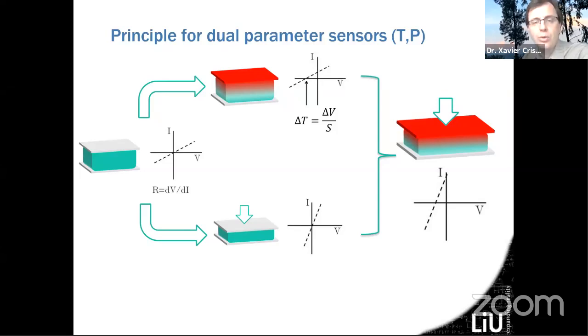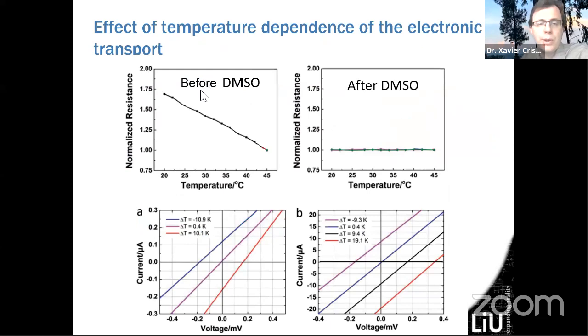Is it possible to do? This is what we succeeded to do, but at the beginning we did not succeed. The aerogel material we formed actually had this kind of response. You see here, this is the IV curve at different temperature gradients. What you see is that the slope is changing while we are not applying any pressure here.